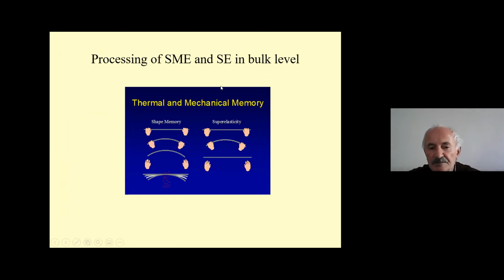In the shape memory effect, the material is deformed in the low temperature condition. This is plastic deformation, and after releasing, the material keeps the deformed shape. On heating, the material recovers the original shape and cycles between original and deformed shape on heating and cooling. In superelasticity, the material is stressed in the parent phase region and recovers the original shape after releasing, exhibiting elastic material behavior.